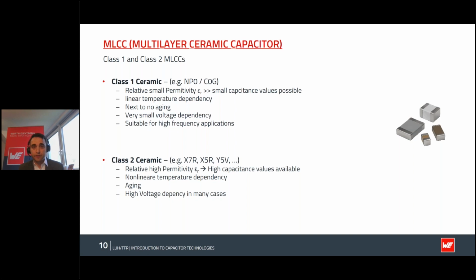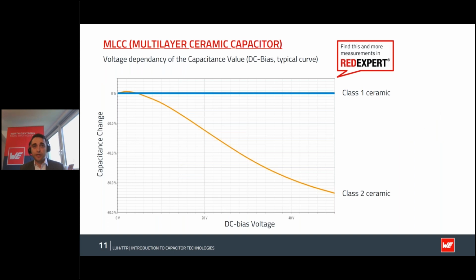So you see, the further down you go, the higher the effect gets here. So they are showing dependencies when it comes to temperature. They also have aging, and they are depending on the voltage, so they have a significant DC bias derating. To show that to you a little bit further, we go to this measurement here. You can see this on Red Expert, and you see in blue we have a class one ceramic, and you can basically see the entire capacitance is available over the entire voltage range. When you compare this to the orange line, which is a class two ceramic, you see the higher the voltage you apply, the smaller the actual capacitance you can use gets. So these effects depend on the ceramic you use.